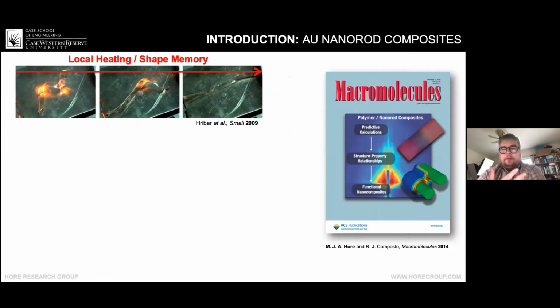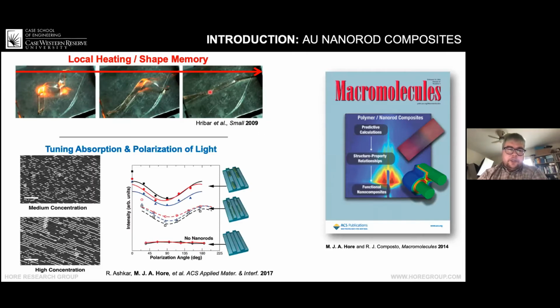Now, the equilibrium shape that the material wants to have is this elongated state. By shining a laser at the appropriate wavelength onto the nanocomposite, the gold nanoparticles cause it to heat, and that heat can trigger the shape memory transition. We can also use these to create long strings of nanoparticles that can act as polarizers and further impart some kind of optical response to our materials.